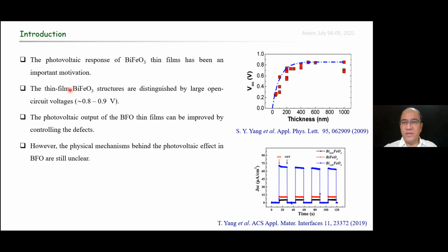Recent studies have shown that its photovoltaic response can be improved by controlling the defects, as observed in this figure for BFO thin films with different bismuth stoichiometry. Despite these advances, the physical mechanisms behind the photovoltaic effect in BFO are still unclear. So it is essential to review the origin of these defects in the BFO system to understand their role on the physical properties and to promote the desired technological advances.